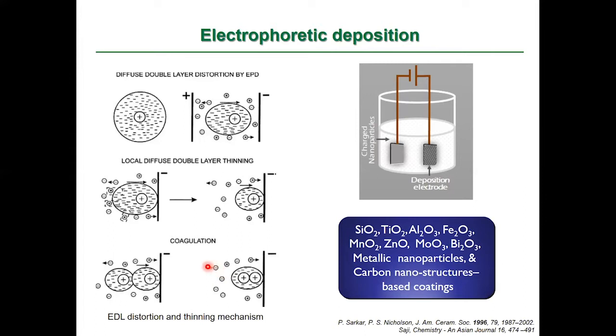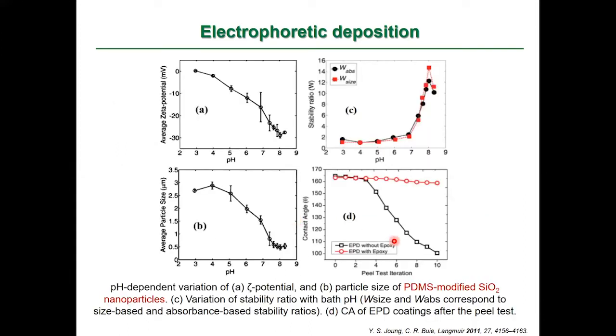And this is the most widely used mechanism for explaining the process of electrophoretic deposition. It is called diffuse double layer thinning, the double layer thinning and subsequent coagulation and thereby the deposition of the charged particles on the surface. This shows an example where a low surface energy material, polydimethylsiloxane-modified SiO2 nanoparticles, was used for deposition. You can see that the electrodeposition process depends on suspension related properties like particle size, dielectric constant of the solvent, charging agent, zeta potential, colloidal stability. Also, it depends on the deposition parameters like voltage, time, conductivity, etc.